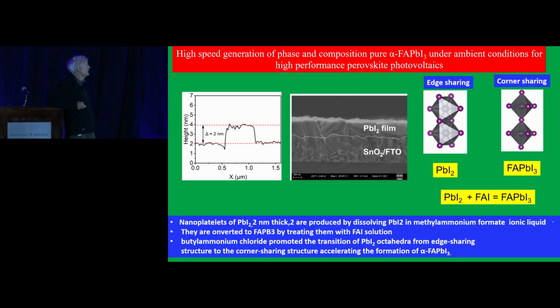So how can we make phase pure and also composition pure FAPbI3 films using this conversion method? Again, the challenge is, you see the start with PbI2, which has edge sharing octahedra. And so if you want to convert this to the formamidinium lead iodide, you have to break one lead iodide bond. And you get the corner sharing octahedra. And that reaction is catalyzed by chloride.